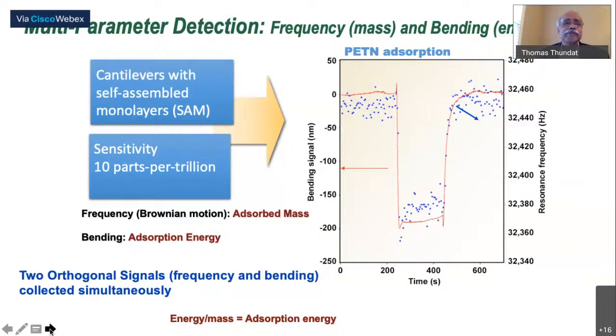This is a simple example of multi-parameter detection. So let me explain. This PETN is an explosive that the shoe bomber used for terrorist activities. So now you have a cantilever that is modified with some kind of chemically selective agent on the surface, like a self-assembled monolayer, or, for example, a polymer or something. And when this molecule, PETN, comes in and adsorbs on the surface, it changes the free energy. And the bending is shown here as a function of time. This is the point of injection of the PETN without changing the flow rate.